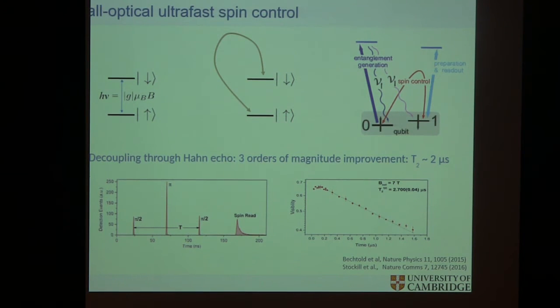And the spin echo, if we do a spin echo on the electron, a pi over 2 pulse, pi, pi over 2, and read out, we're operating around 3 microseconds. Now, this is the fundamental limit. We can't get better than 3 microseconds. So anytime you talk to any quantum dot people, they'll say, yeah, it's on the order of 3 microseconds, but that's it. It's fundamentally dictated by the strain dispersion experienced inside the quantum dot, affecting the quadrupolar couplings of nuclear spins, in turn affecting the electron. Okay. So it is complicated as a system, which is fun to study as a physics problem, but it's terrible if you want to extend it. But what this says is that 3 microseconds is all you have, and don't even try dynamic decoupling, essentially, for this purpose.